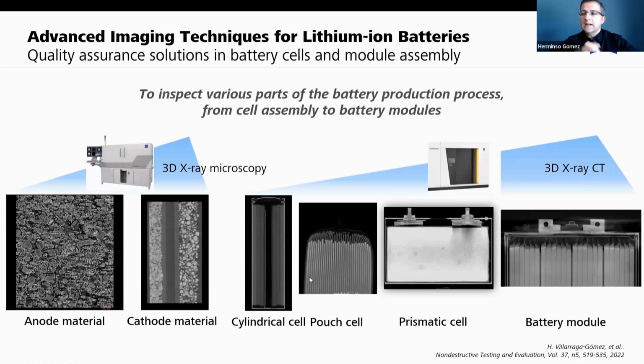When you get into very large batteries, then we're talking about something that can penetrate deeper into the materials because you have a thicker component, and then we would have to use X-ray CT. The difference between them, both being X-ray technologies, is the penetration power. X-ray CT generally can crank the kV voltage higher, to 160 to 225 or more, and that gives you the ability to go through prismatic cells and battery modules. X-ray microscopy doesn't raise the power so high, so it can keep the resolution at a very high level.